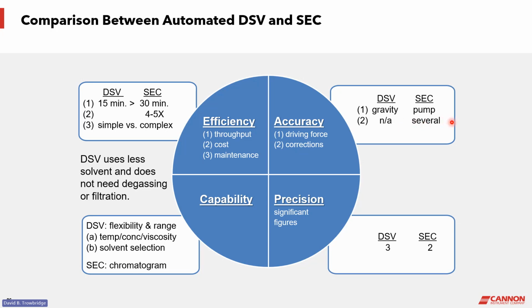For SEC, there's several steps to the procedure that introduce uncertainties, like drawing the baseline, a very fundamental part of it. There's a selection criteria that has to be decided on, and you will lose some of the peak if you select one way, but you may incorporate noise in the baseline if you select on another basis. So even that by itself is introducing uncertainties, and that could allow us to talk about the precision. Those uncertainties accumulate and allow a situation where we usually see SEC having less precision, fewer significant figures than we obtain in the dilute solution viscosity measurements.